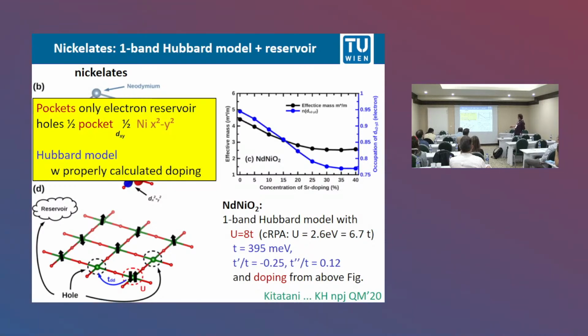Now, if you strontium dope the system, some of the holes go here, some go here, and if you look at the slope, it's about 50-50. 50% of the holes, roughly speaking, go to the reservoir, 50% to the Hubbard model. We have then calculated from ab initio all the interaction and hopping parameters for this one-band Hubbard model, and this translation of strontium doping to the occupation of the x squared minus y squared orbital we still need. Okay. So that is our description, and then I will continue with that.